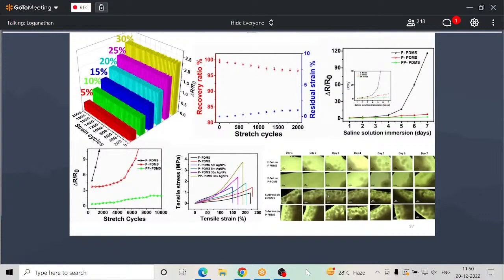And here we can see the strain sensor results over 2000 cycles. They are very stable, with very small hysteresis, and you can see the recovery ratio performances. And we also study the cell viability, because we know that this kind of wearable device we are going to put onto our skin, so it may have some cytotoxicity that will affect our human cells. So we have to study those things. So we try to simulate those things with the L929 cells, and then we also study the antibacterial effects, because we know that silver nanoparticles exhibit antibacterial properties. So these devices can sustain very good durability and also have very good cytocompatibility.